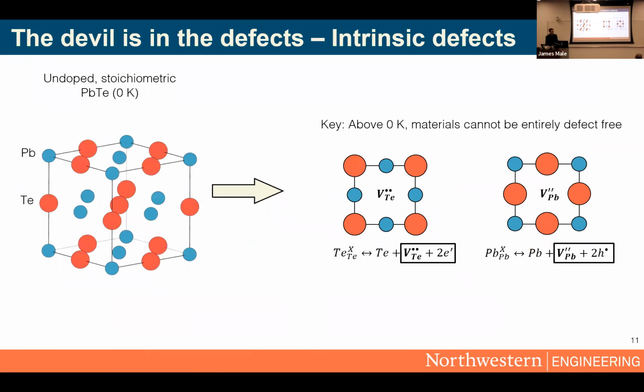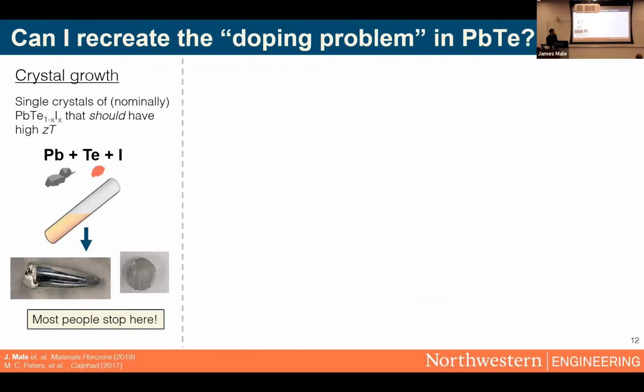So before I get into that, you might already guess I'm going to talk about defects being responsible. So I want to just do a brief introduction to the basic defects in lead telluride. So at 0 Kelvin, lead telluride might be this nice, perfect rock salt type structure. But like any material above 0 Kelvin, entropy necessitates that some defects form in the lattice. In lead telluride, the most common of those defects for the undoped samples are tellurium vacancies and lead vacancies. Now, because lead telluride is kind of a semiconductor, these vacancies are charged and each of them donate different types of carriers. So tellurium vacancies give you electrons, lead vacancies give you holes. So you can kind of already expect this should affect your doping properties as well. So that's what I sought to explore.